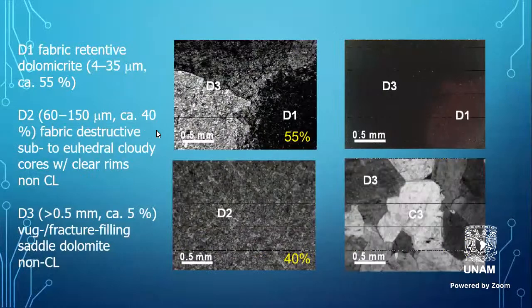In petrography, three generations of cements were identified there. The first generation I call D1. It is dolomicrite and it is fabric retentive. It shows here in plane polarized light, as you can see, the fabric is preserved there. The size of the grains is between 4 to 35 microns. Visually estimated, its abundance in the entire core is about 55%.